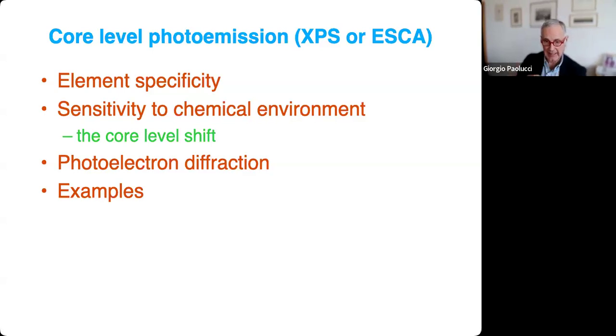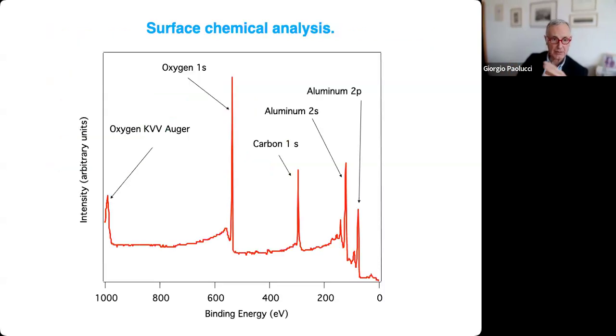So if you take a piece of aluminum as it is from air, and you put it in your vacuum chamber, you measure something like that. So this is aluminum. And as you can see, aluminum is not the highest peak. You get a huge oxygen 1s peak, and you get a relatively big carbon 1s peak. And this is because of contamination. And the reason is, as you know, aluminum oxidizes very easily.